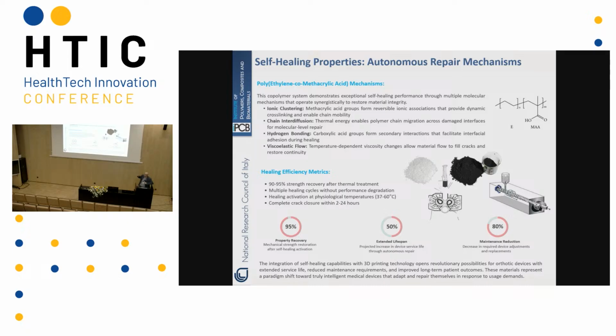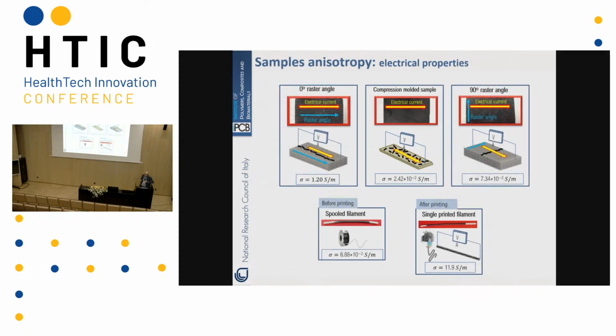And of course, also during the printing, the presence of small molecular weight filler has the ability to diffuse around the layer and increase the adhesion between the different layers. It allows the complete recovery of the mechanical properties of this system. Okay, this is just one example.